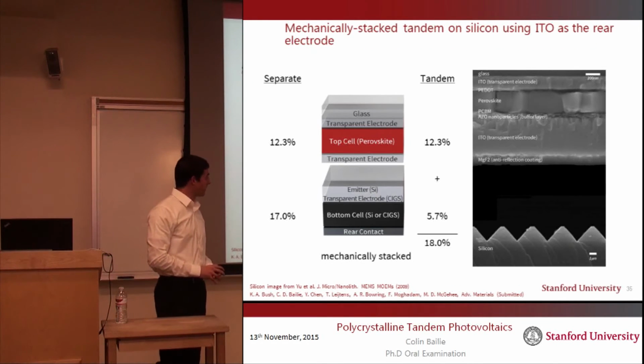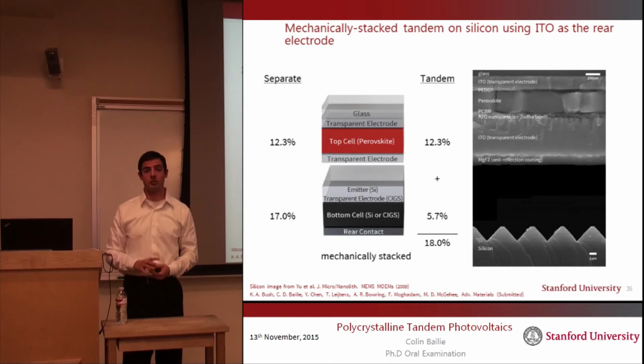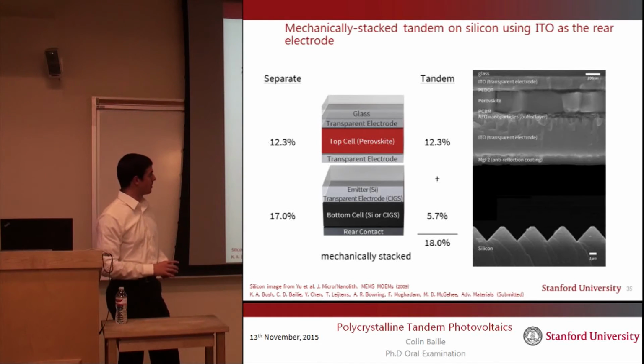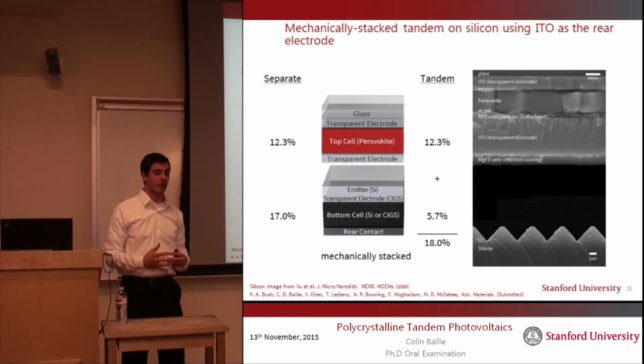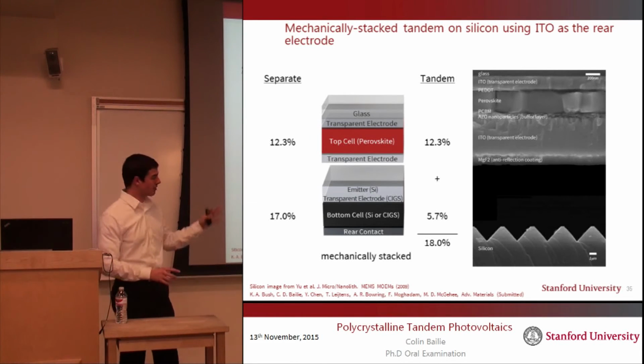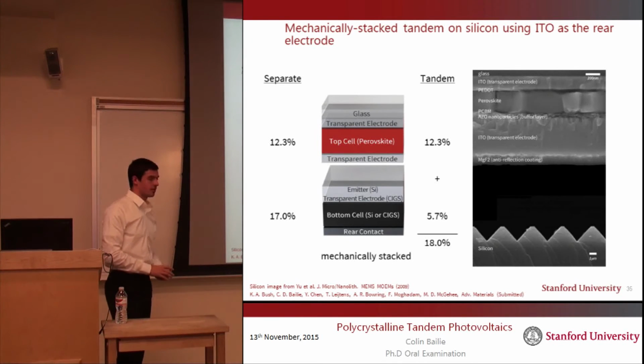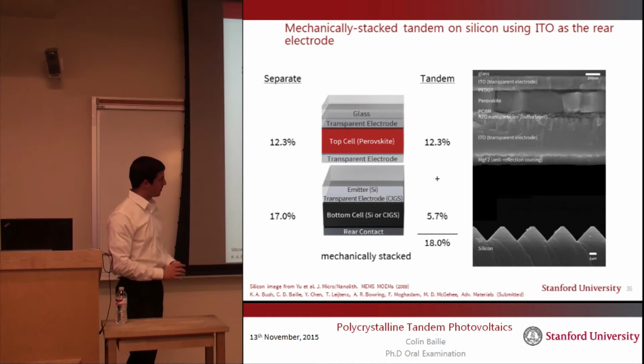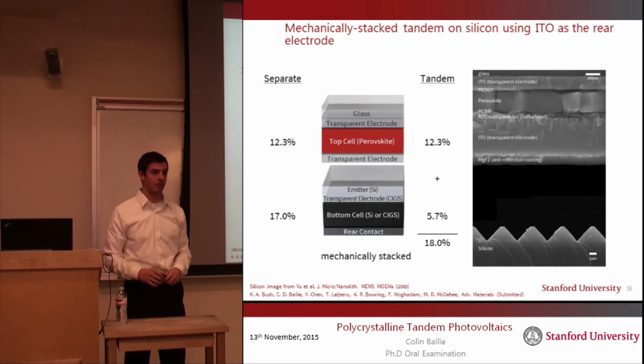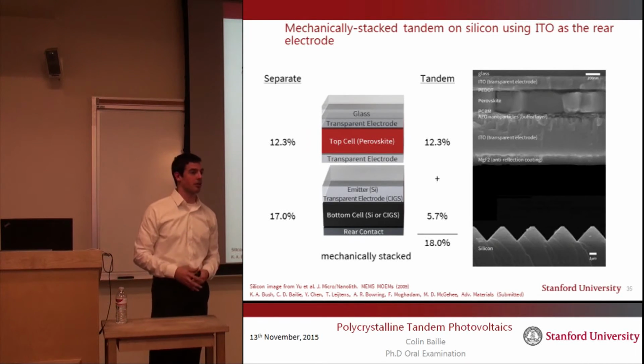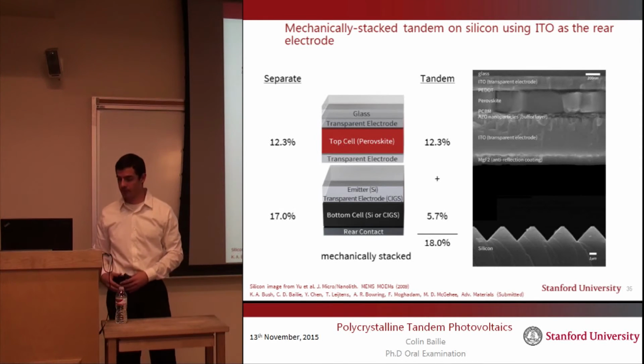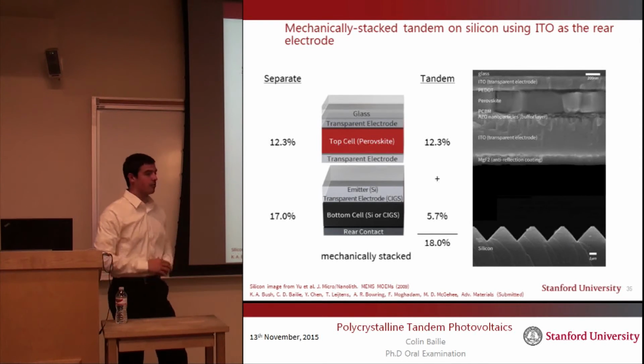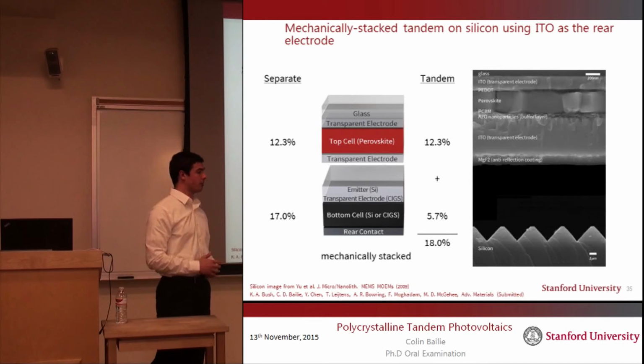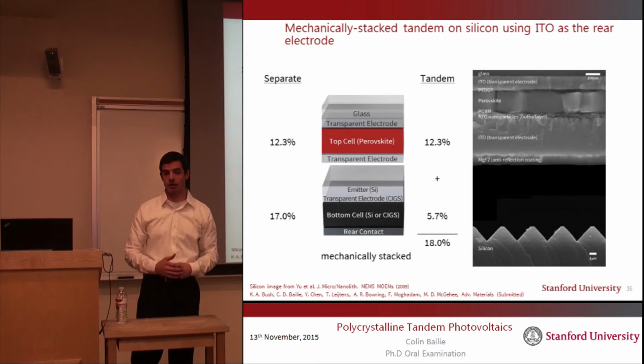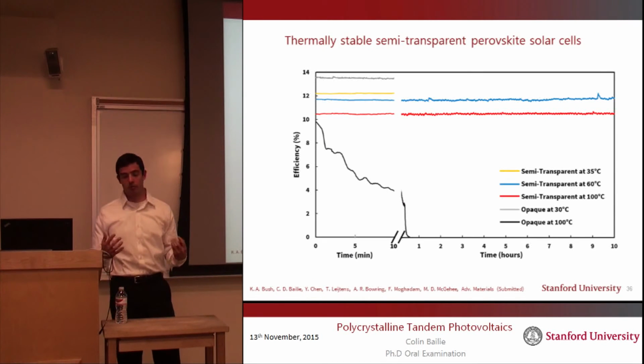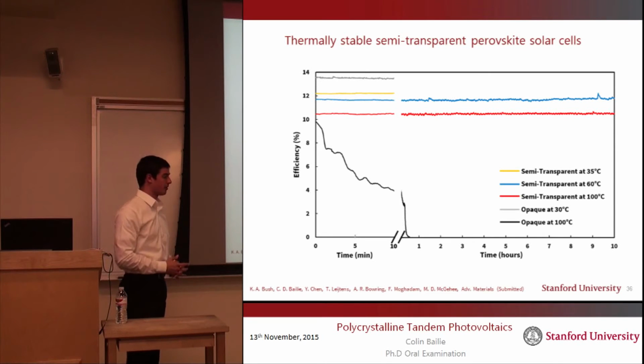And so we made a mechanically stacked tandem with this transparent perovskite solar cell as well. Again, about a 12.5% semi-transparent perovskite solar cell. And this time we stuck it on a 17% silicon solar cell, just to illustrate that you can keep the texturing in the silicon solar cell that you would like to have there. And so the tandem that we made was 18% efficient, which is again a moderate improvement on top of the silicon solar cell by itself. But more importantly, what we made was a stable perovskite solar cell.